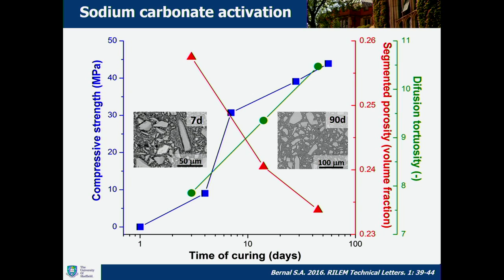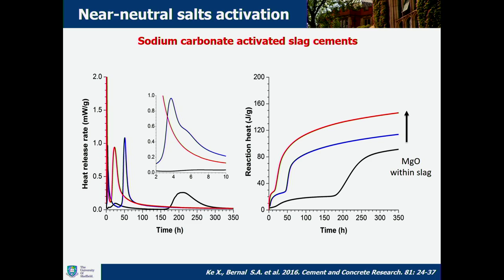So we did a very detailed analysis of these materials from day one up to 180 days, and we identified that effectively at very early times of curing, the material is very heterogeneous, is porous, which is consistent with the low mechanical performance. However, at later stages of reaction, we can see the material is very homogeneous, very dense, consistent with the increase in the tortuosity, increase in mechanical performance. So the question was, what's driving this? Will this be the case for any slag in the world? And the answer is no.